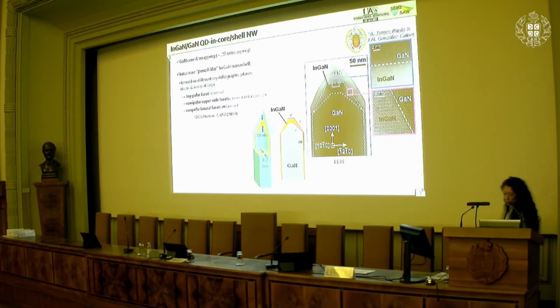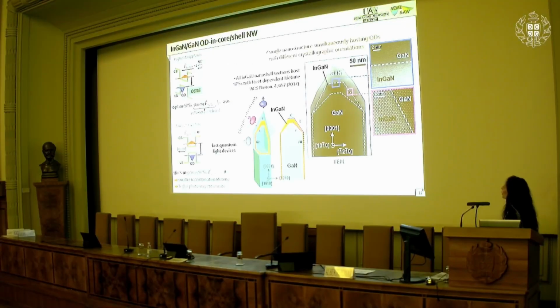As I will show you in the continuation, all three sections of these nanowires contain quantum dots that are responsible for the emission of single photons. Now, this is actually the first experimentally demonstrated single nanostructure that is capable of simultaneously hosting quantum dots that were grown on different crystallographic facets, so with different crystallographic orientation.